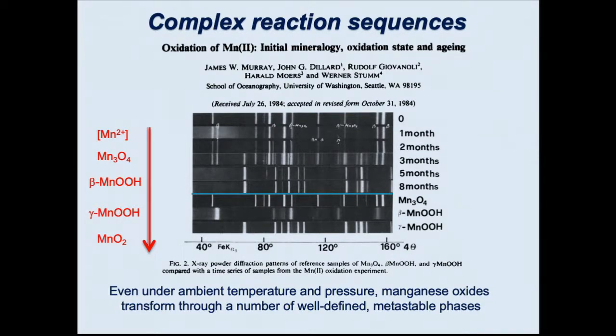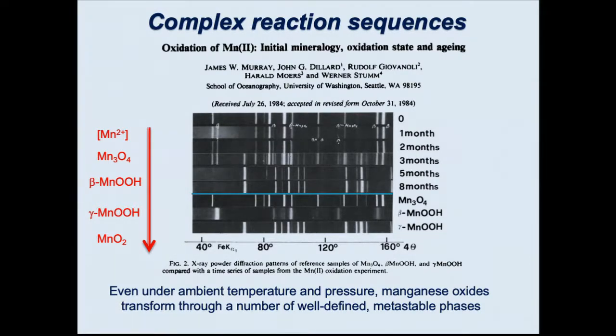But also maybe if you see these diffraction films, for those of you who are older, the way people did diffraction, this is an interesting experiment. So this is a manganese 2+ precursor in aqueous solution, and they just leave it in there. There's nothing changed to it, and they look at what happens over months, and they take the diffraction pattern. And here's what happens. So in the beginning, you have manganese 2+ in solution. The first phase you form is Mn3O4 spinel. And if you just let it sit, it forms beta manganese oxyhydroxide, then it forms gamma manganese oxyhydroxide, and then